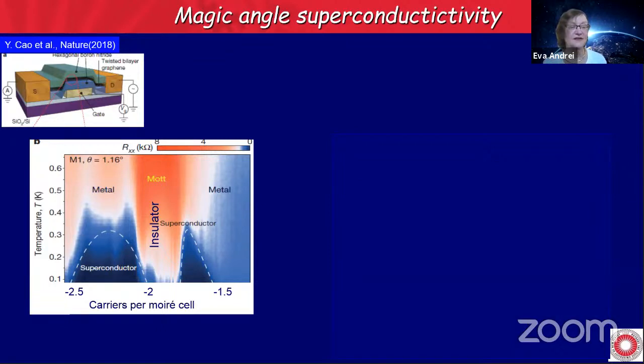This is in a dilution refrigerator, and they measure the transport properties as a function of filling. The vertical axis here is temperature, and the color code is for resistance. They saw that at a filling of -2, which is about when you have 2 electrons in the whole band or 2 holes in the whole band, you get an insulator. But as you move off that filling just a little bit to either the right or the left, the material becomes superconducting. And this was absolutely a huge surprise and excitement.